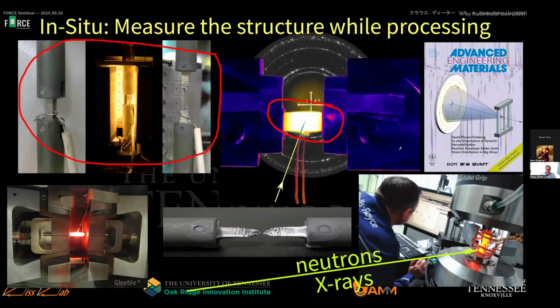Right. So what we want to do is to measure in situ the structure while we do the processing. These are pictures of zirconium alloy under tensile testing at the APS beamline, normal grain size. So I won't have time to talk about that today. This is titanium aluminide, which we heat up to 1400 centigrade and do diffraction in situ. So this is a false color, black and white photograph. And behind I put a diffractogram. And the setup is relatively easy. So you have an incoming beam at the synchrotron, which is fine bundled. Then you have a specimen. It can be in a furnace. It can be in a load frame. And we record the Debye rings in the distance. This is a Gleeble thermo-mechanical processor. I would love to see that in a beam one day. And what we do during the heating, during the operation, we do the diffraction with neutrons or with X-rays.